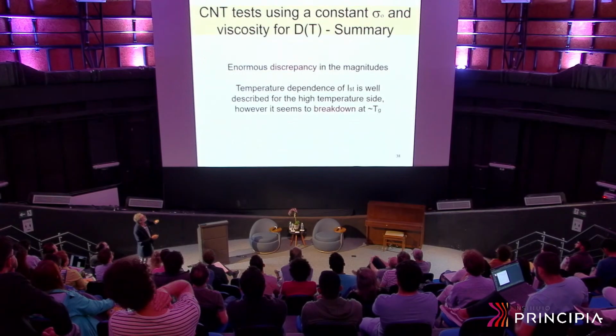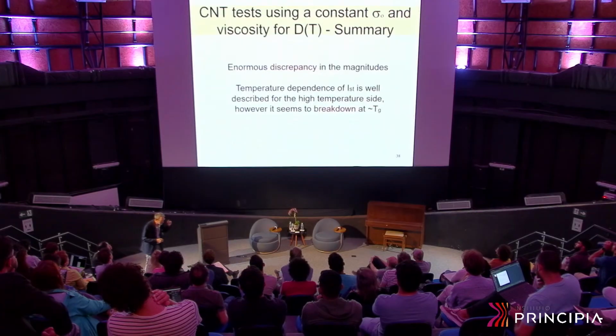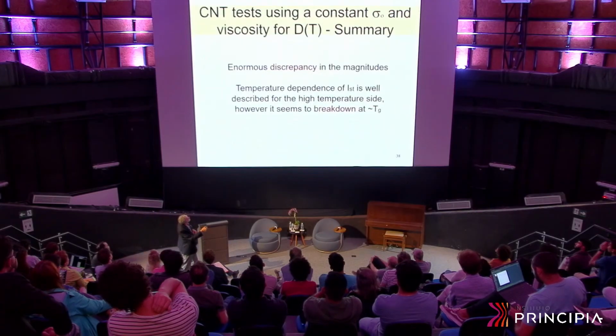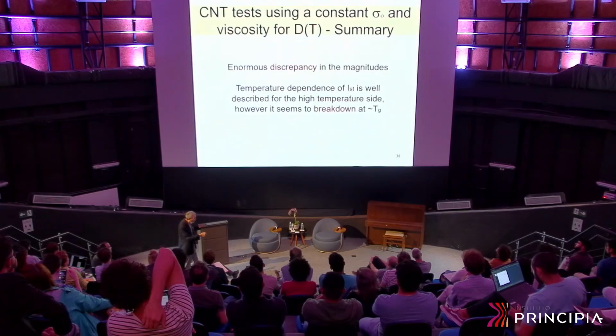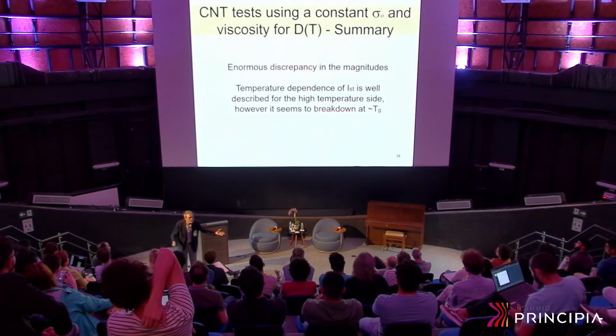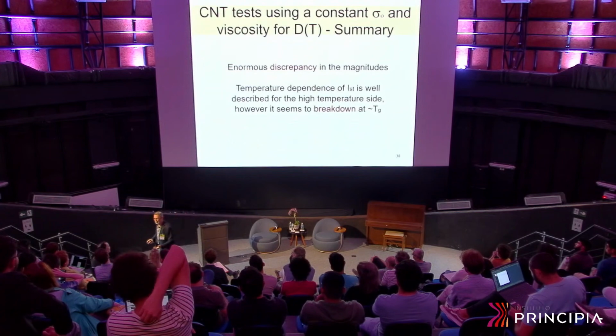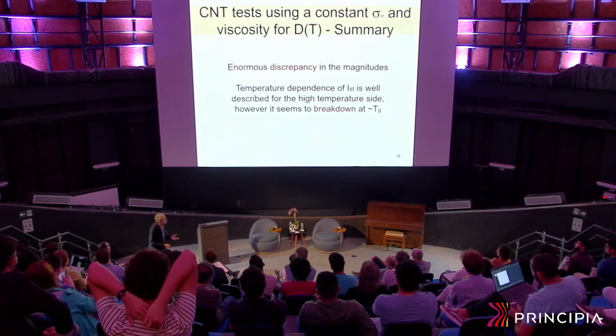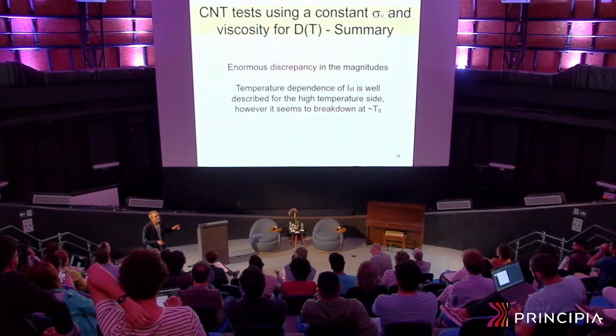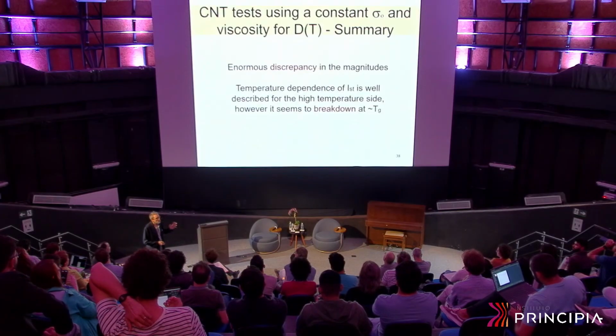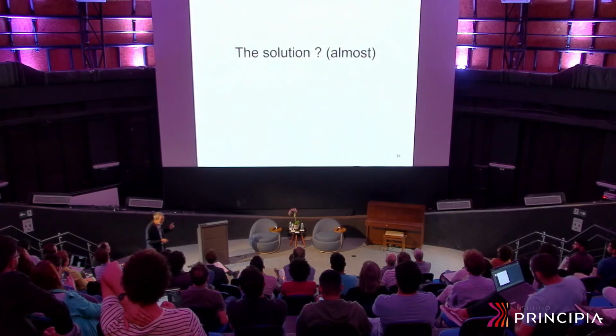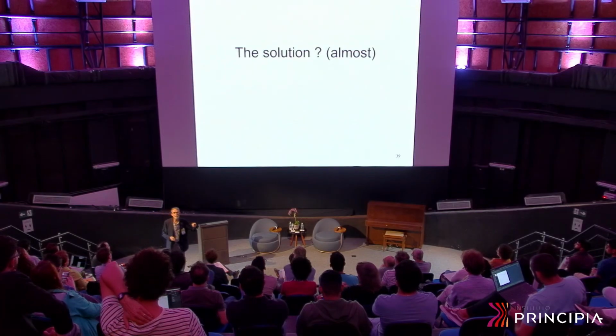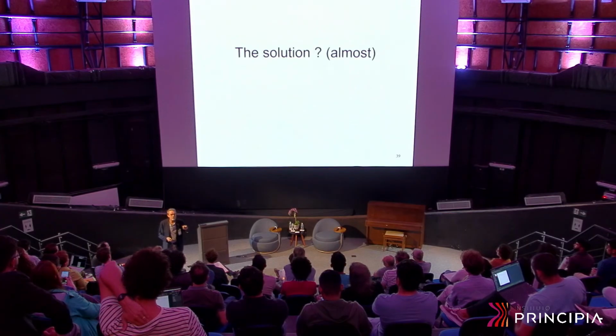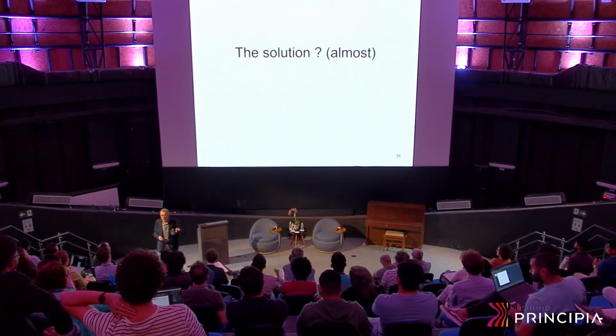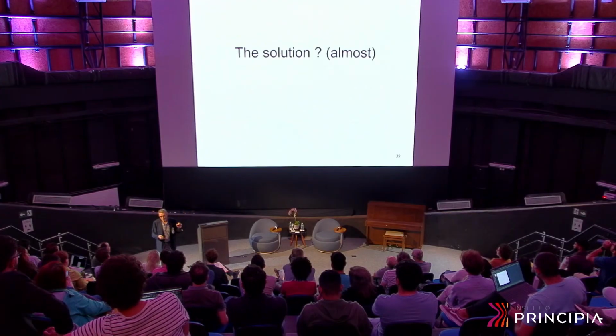So, enormous discrepancy. However, we had one adjustable parameter. In all those papers, sigma is unknown. It's an adjustable parameter. And so none of those were definitive tests of the theory. So we had this one adjustable parameter. Second thing, nobody had measured the diffusivities. Everybody was using the Stokes-Einstein equation, using the viscosity as a proxy for the diffusivity. So there are two problems, at least, with these kind of tests.